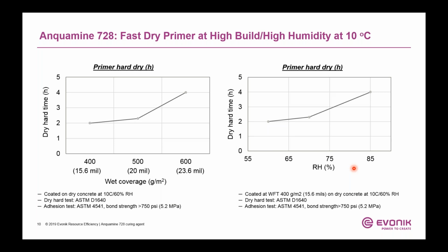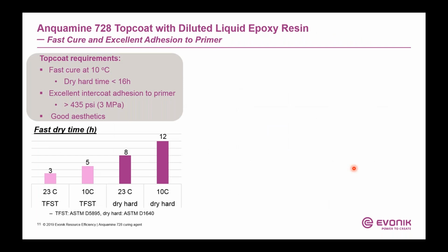So far, I have shown you that the Anquamine 728 primer meets the fast dry requirement, and also has good carbamation resistance and excellent adhesion to substrate. So what about the top coats? For a floor system, you need a primer and a top coat. So what are the requirements for top coats? For the top coat, in order to meet a 1 day floor system, obviously it also has to be fast cure, but it doesn't have to be as fast as the primer, because with a top coat within 24 hours, you still have enough time for the primer to dry.